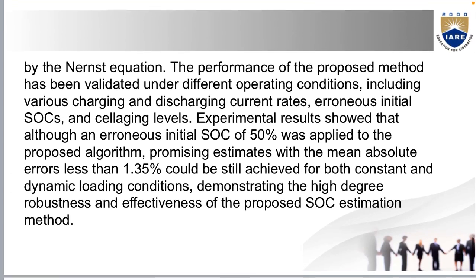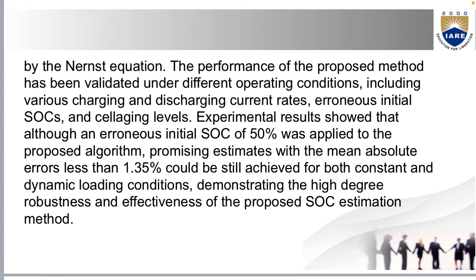quantitatively deduced by the Nernst equation. The performance of the proposed method has been validated under different operating conditions including various charging and discharging current rates, erroneous initial SOCs, and cell aging levels. Experimental results showed that although an erroneous initial SOC of 50% was applied to the proposed algorithm, promising estimates with mean absolute errors less than 1.35% could still be achieved for both constant and dynamic loading conditions, demonstrating the high degree of robustness and the effectiveness of the proposed SOC estimation method.